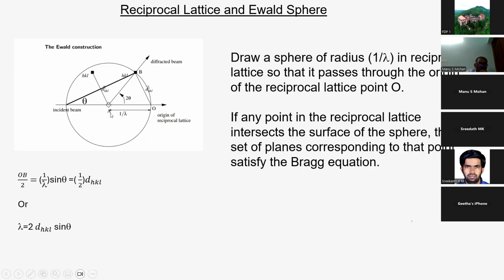How to draw the Ewald sphere is something very interesting. It is even very difficult for me to understand now, but I got a small glimpse of it. 1 by lambda is the radius of the Ewald sphere. With that, you draw a sphere with O as the origin of the reciprocal lattice. This is the incident vector, and suppose this is the diffracted vector AB. That will also have the same magnitude. Why does it have the same magnitude? Because it's an elastic scattering. Energy is conserved, so you have the same magnitude.